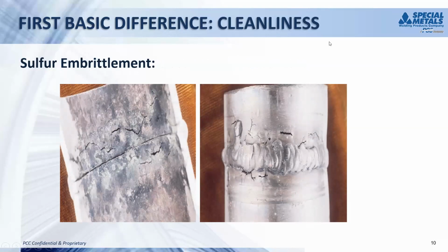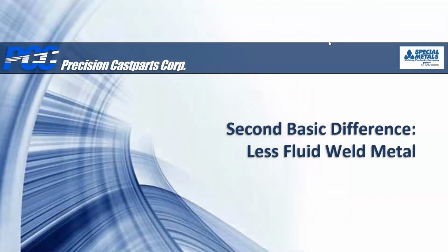And this example is probably the worst we've ever seen, so we wanted to put it up. But this is a nickel 200 tube, and typically nickel is used a lot in the caustic industry. But you can see that there was sulfur on the surface of this material, and it was TIG welded, sort of, but you can see the kind of cracking that you get. So sulfur forms a eutectic with nickel and forms low melting areas, and it just kind of falls apart while you're welding. Next slide.